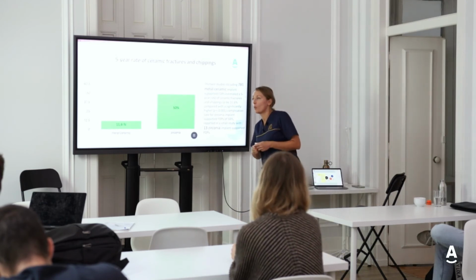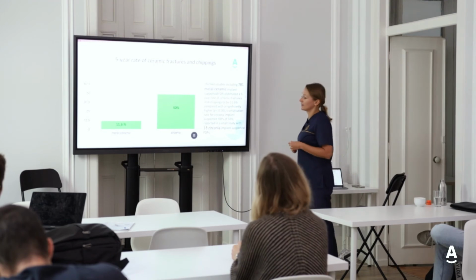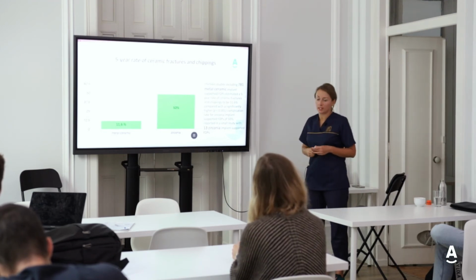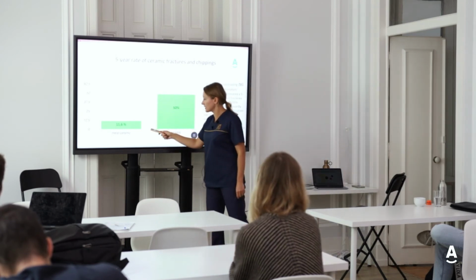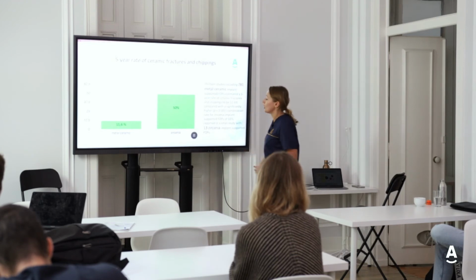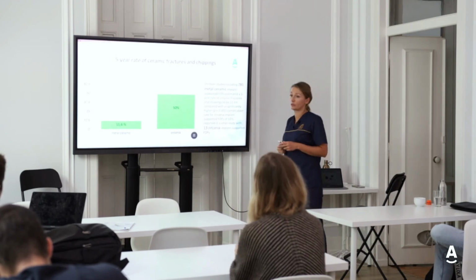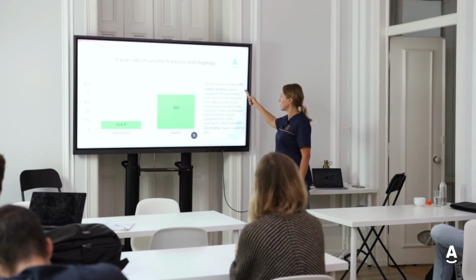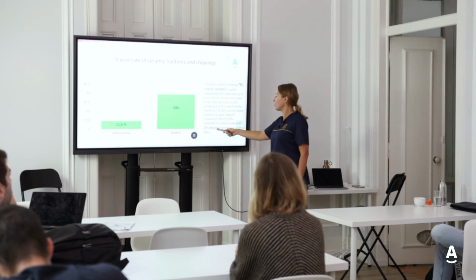Nevertheless, some differences were found in the technical complications. So fractures and chippings were studied, and in 5-year rate we had 11.6% technical complications for metal ceramic, comparing with 50% for zirconia. But we should pay attention that the study was based on 781 metal ceramic units, comparing to only 13 pieces of zirconia.